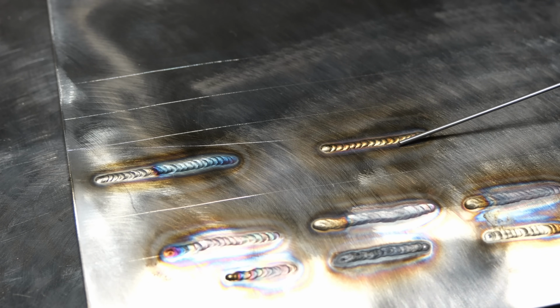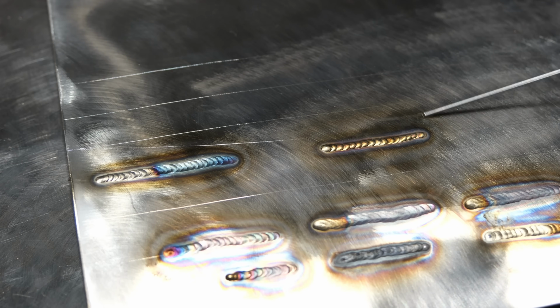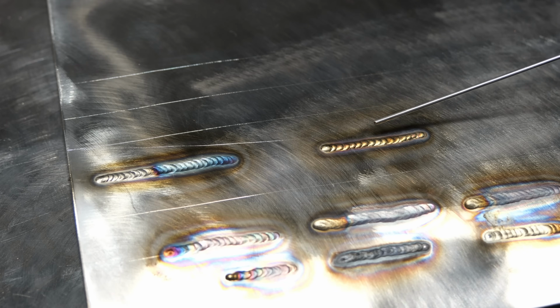This was very sluggish to get going. You can see how cold this section is. I had to slow my travel speed, but only 5 amps difference between these two, and the beads look completely different. So realistically this would need to be welded somewhere around 27 amps to get, I guess, ideal for a bead on plate. Keep in mind, if you're welding two pieces of stainless together and not just a bead on plate, you're going to need more amperage.